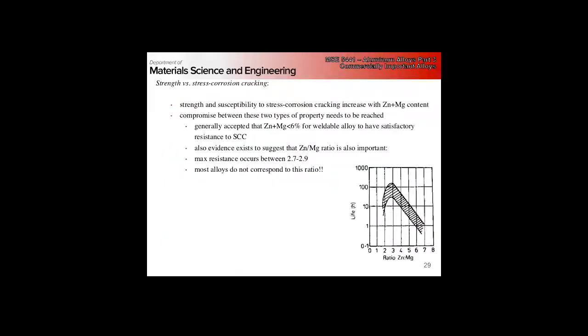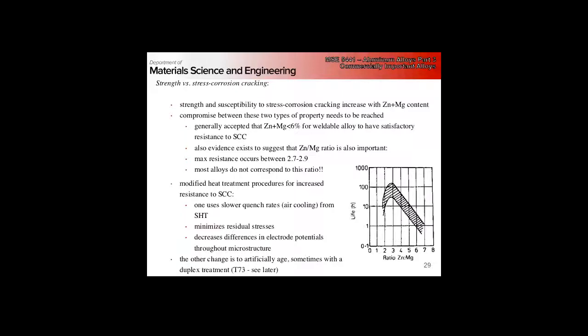We pointed out that there is a critical ratio of zinc to mag where we have the best stress corrosion cracking resistance, and I pointed out that most commercial alloys that we use actually don't fall into this ratio. Instead, we use modified heat treatment procedures to increase this resistance.